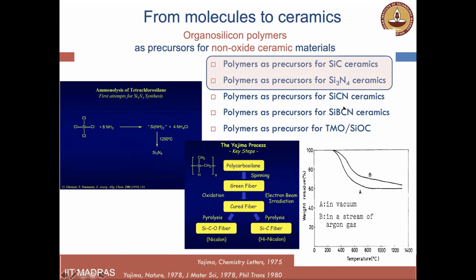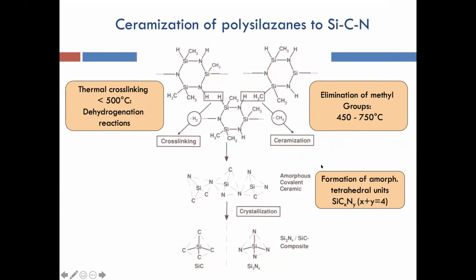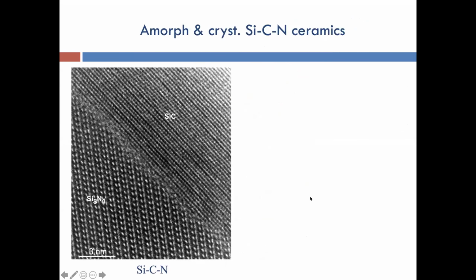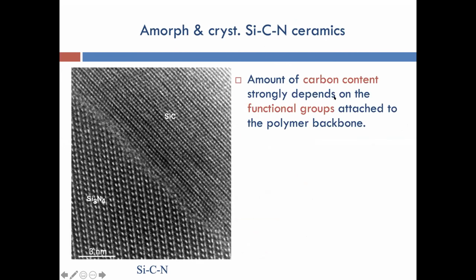In any case, we later moved from just carbides and nitrides to silicon carbonitrides, hoping that silicon carbonitrides can be used for extreme temperatures. I will show you in the next slide that when you use polysilazanes to make them, you can get silicon carbonitride composites, basically containing silicon nitride and silicon carbide, at around 1500 degrees Celsius. But the problem is that these are highly crystalline materials, and when you make them through a precursor route, you always have some free carbon. Depending on the amount of free carbon, which again depends on the functional groups attached to the polymer backbone, the silicon nitride decomposition reactions are governed by the carbon content that is available.